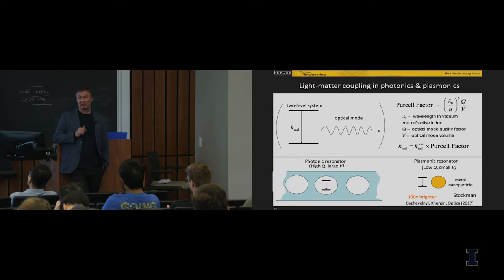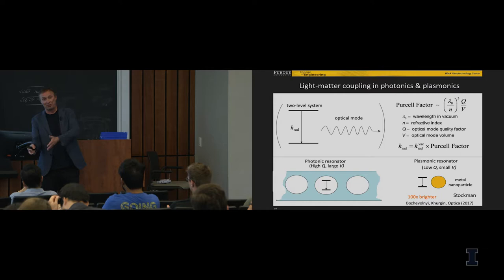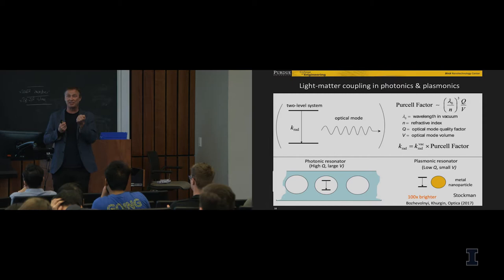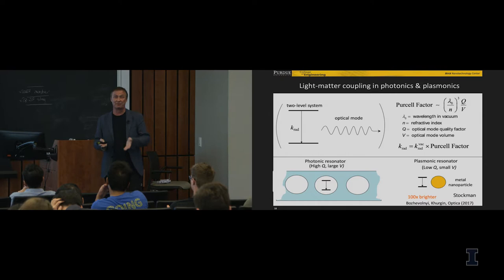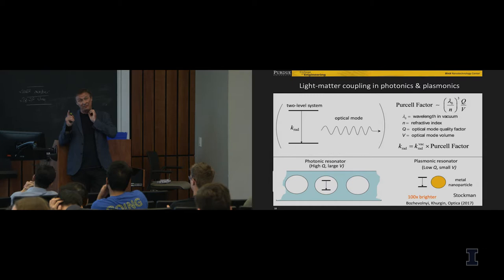Basically, by using so-called gap plasmons, you could confine electromagnetic radiation down to 5 nanometers. If you compare it to 500 nanometers, it's 100 times smaller. Since you have volume here, you have a million-factor enhancement just because of the confinement. An additional enhancement in the range of 100 comes from the quality factor, which is around 100. But the fact that the quality factor is not large is exactly what we need.